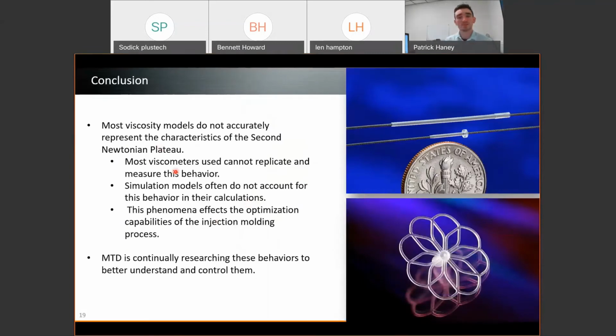It's understudied because a lot of the viscometers that we use in the industry can't replicate those kind of characteristics. They can't replicate velocities at that speed, at channels that small, and shear rates that high. So the practical hands-on tools that we use to measure viscosity differ from the characteristics that we see when we expose these things to extremely high injection pressures and shear rates in our injection molding machines.